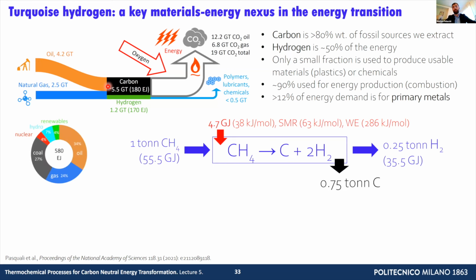This is exactly the point of producing turquoise hydrogen. Let's say we take 1 ton of methane. This is worth 55 gigajoules of energy. We provide 4.67 gigajoules of energy to crack methane down to carbon and hydrogen. Overall, this is 38 kilojoules per mole, compared to 63 for steam methane reforming and 286 for water electrolysis. So it's a huge gain in terms of the energy duty required for the cracking reaction to occur.